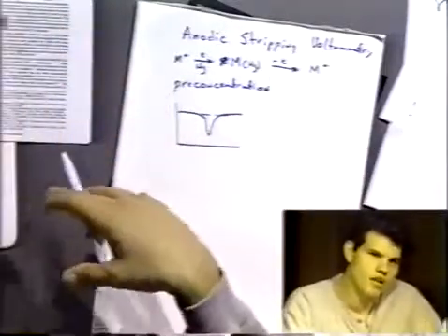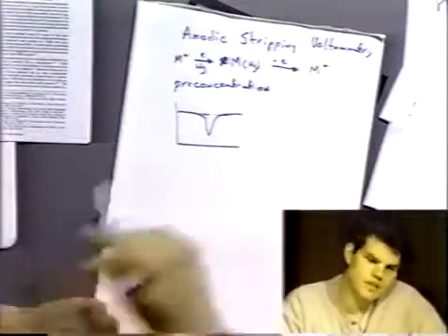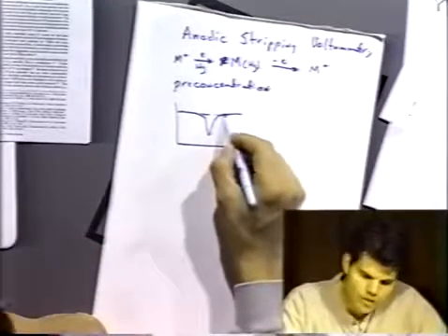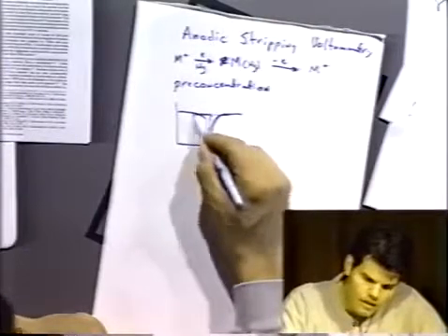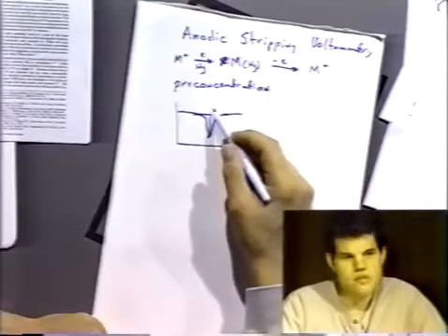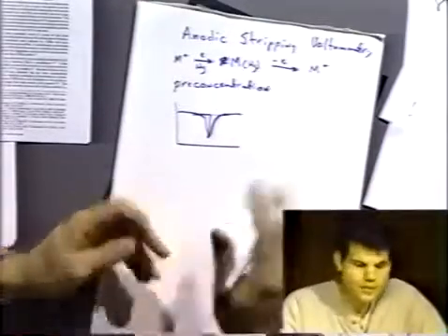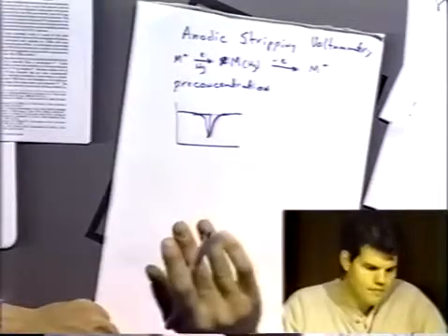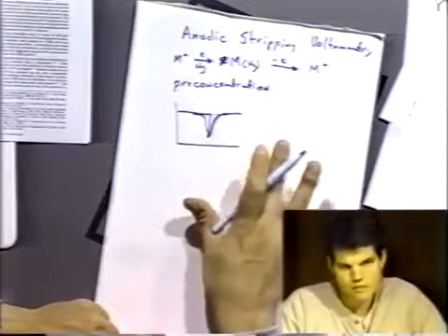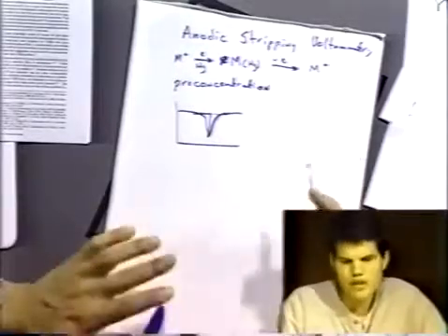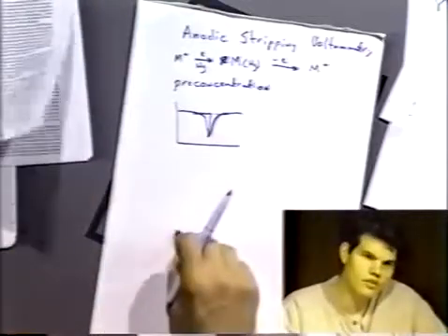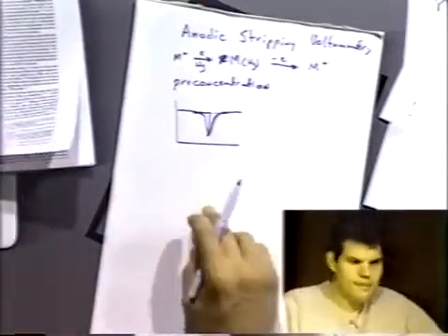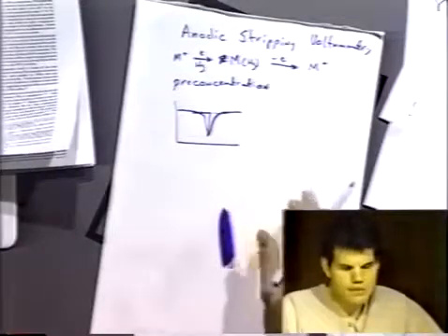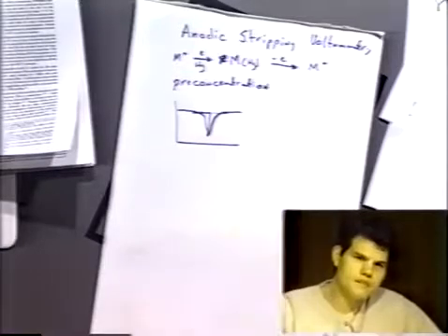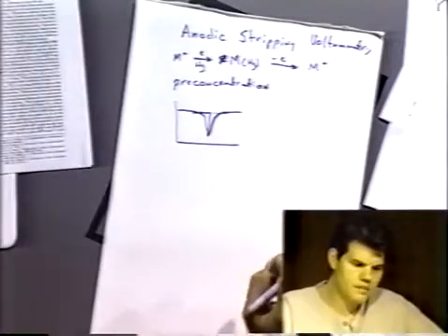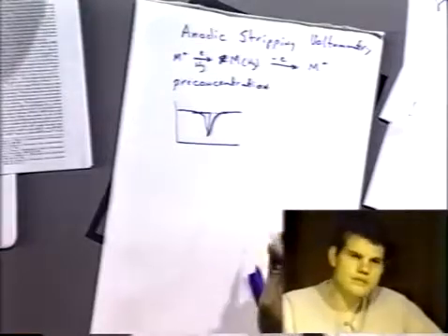We can actually physically remove all the metal that's in the mercury drop, and so what you'll see is a wave like this, or perhaps a wave that even looks different, where you see a very sharp drop to zero when all the material is depleted in the mercury. So it's a method in general for sensitive metal determination, and it's usually very inexpensive, and it's comparable in accuracy for certain metals to atomic absorption spectroscopy and inductively coupled plasma methods, which are much more expensive methods.